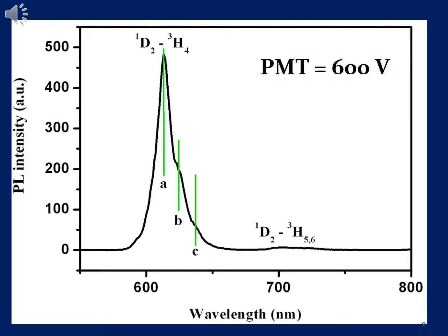At room temperature, when we measure the optical response of our sample, we observe a single red emission from the 1D to the 3H electron transitions. Now this clearly proves the effectiveness of the intervalence charge transfer that exists in our material, which is orthorhombic.